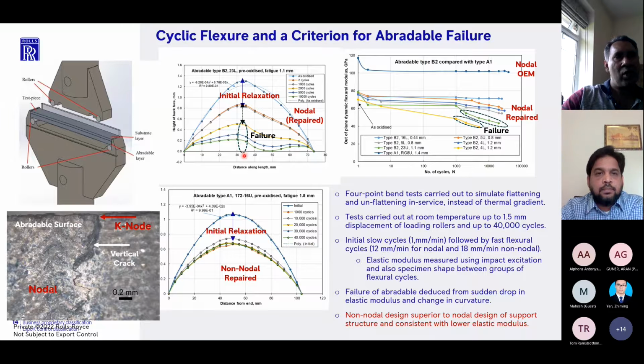So as the number of cracks form and begin to grow, you get permanent deformation and therefore a permanent change in shape. And there's a sudden change in shape that occurs, which corresponds to a sudden drop in the elastic modulus. So in many ways, what we did was identify a failure criterion for these abradables. The failure criterion was based on a dramatic change in the shape, accompanied by a sudden drop in the elastic modulus. So again, using cyclic flexure, a 4-point bend test, as well as resonance methods, we were able to down select a non-nodal abradable design from a nodal design in terms of increasing the life of the abradable on the segment.